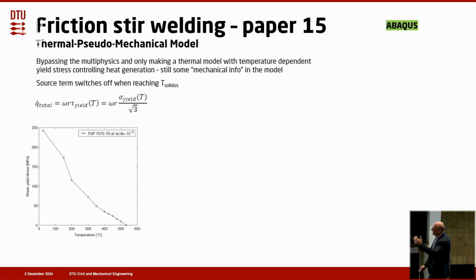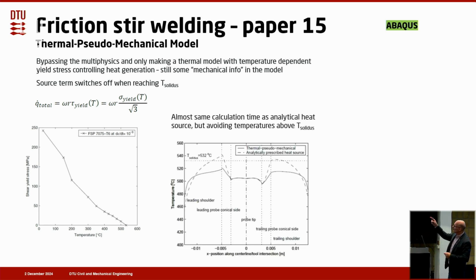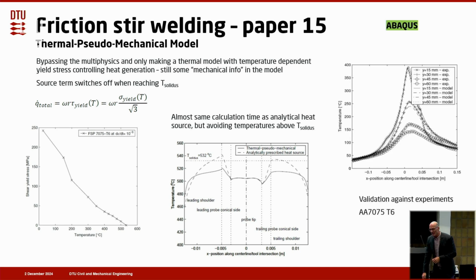And this way we bypassed the multiphysics, and instead of making an experiment so we knew the total heat generation, we tried to make it based on material information instead. So we made a model where the temperature-dependent yield stress was controlling the heat generation. There is still some mechanical information in the model, but it's only a thermal model, which means that it calculates extremely fast. So we got almost the same calculation time as just prescribing the analytical heat source, but then we avoided temperatures over the solidus temperature, of course, because then it switches itself off. And then we did some validation against experiments, and there was actually quite nice agreement.